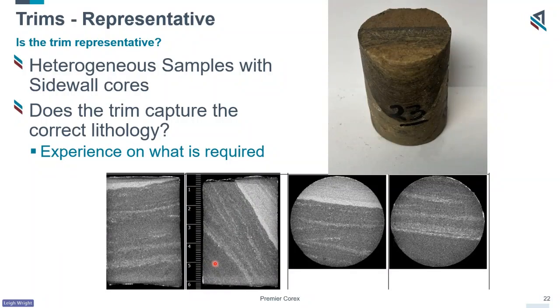And again, I'm going to talk about the importance of CT scanning and sample selection. This sample, if we had more samples, would not be deemed representative to provide useful information. However, doing the scanning and the prep prior to that, you know that this sample might provide slightly different data than you expect, but you can understand the result at the end of the study and know, well, this may be an outlier, and this is why the sample is an outlier.